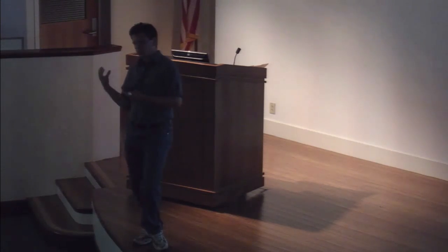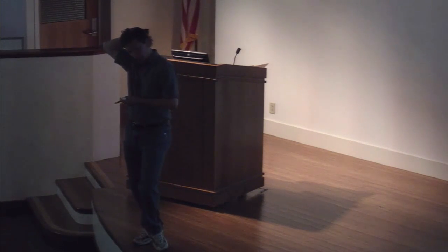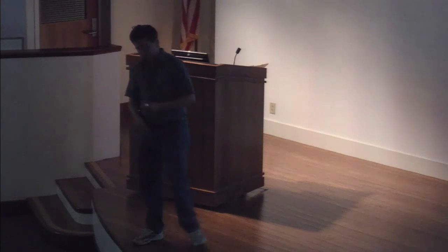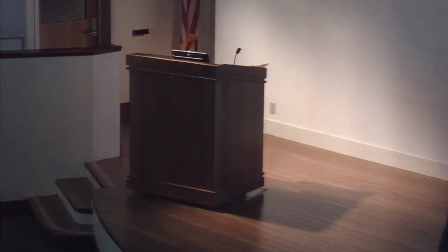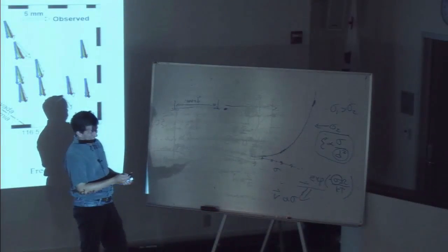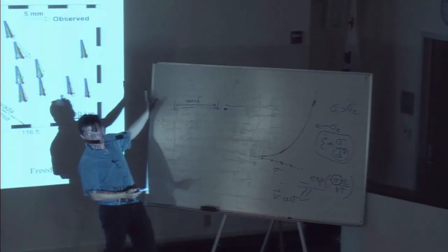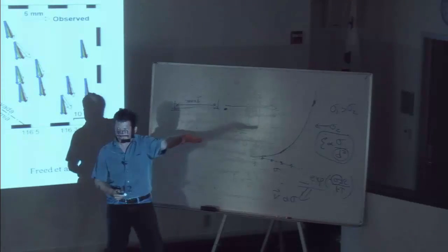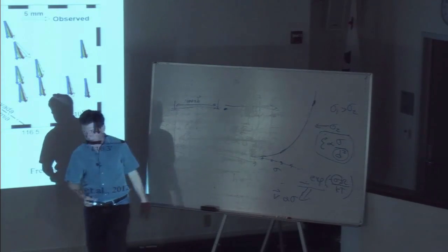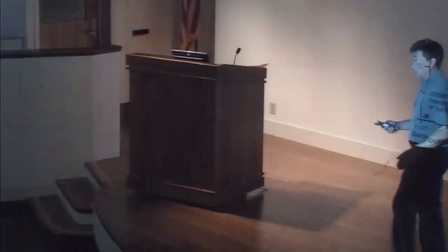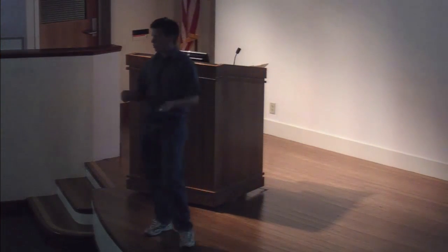And so one of the new things on the vanguard in material science are these things called dislocation cascades or avalanches. And they were discovered in ice, I think, if I remember correctly. So what happens is that instead of being limited by a diffusion process, under some conditions, you can just have a pileup of these dislocations, and they can just blast their way through here. And once that happens, about 10 of them can run through all at once. And so that's one possibility of what's happening deeper in the Earth.